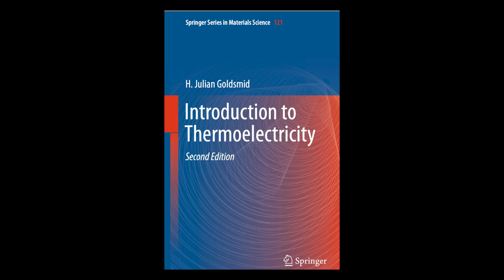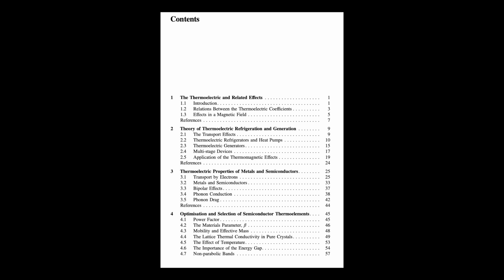The outline mentions the Slack relation, kind of a rule of thumb to estimate LL based on things like Debye temperature, related to vibration frequencies, average atomic mass, and atomic spacing. Gives you a rough idea. So it's this constant balancing act: high electrical conductivity, low thermal conductivity, all interconnected, complex stuff.